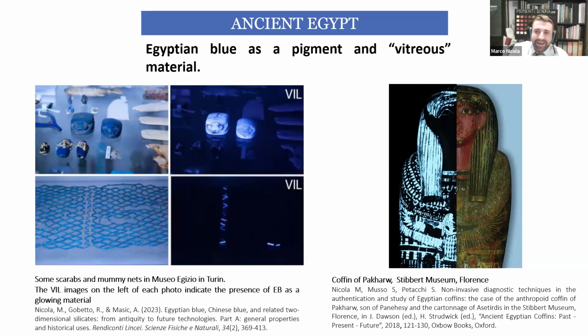So it's a copper-rich glass. But it is amorphous, a proper vitreous material. Instead, Egyptian blue is crystalline, and if you break one of those beads made of Egyptian blue, the core is not white, it's blue, because they are completely made of Egyptian blue. And it's a different technique, different technology, different material, even if they are similar raw materials.